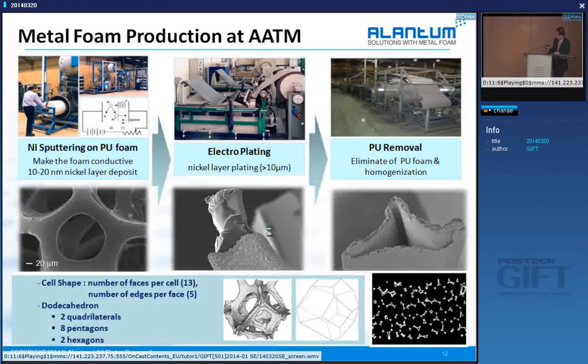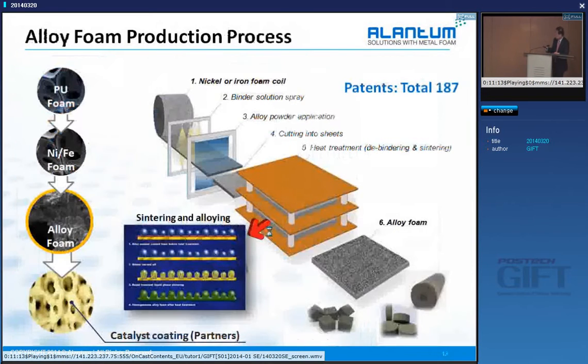But so after making this pure metal into the coil type, then we can move into the Onsan plant. So pure metal coil is fed into this process. Then we can apply the binder solution. Then we can apply our powder depending on like a nickel, ferrochrome, or stainless steel, whatever. Then we can just sinter them. So this is like a powder metallurgy sintering process, okay? Then we can make a final form like this. This is our unique patent process. Through this, we have totally acquired over 187 international patents.